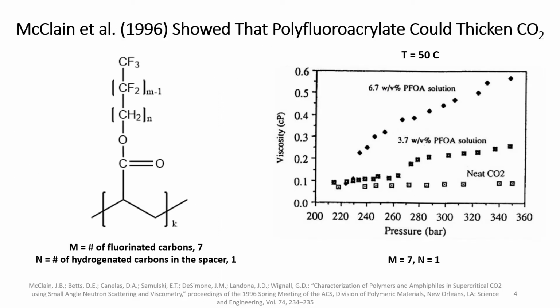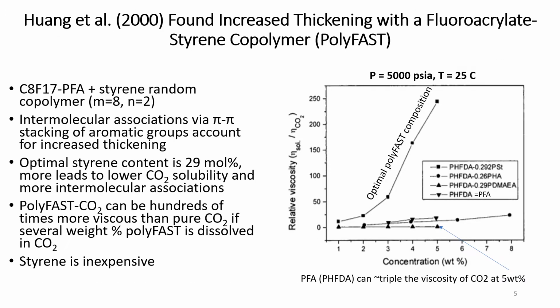In 1996, though, McLean and co-workers found that polyfluoroacrylates, shown on the right, could thicken CO2 substantially, so it became a much more interesting potential recovery additive. A few years later, Huang and co-workers created a copolymer with styrene, named PolyFast, that increased the thickening effect substantially, even to multiple hundreds of times at the optimal composition.